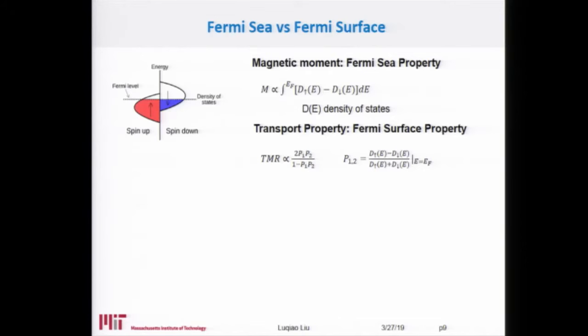For example, we talk about magnetic moment or magnetic susceptibility, and we know that this property comes from the whole Fermi sea. If you want to calculate the total moment of a certain material, you have to integrate over all of the density of states below the Fermi level. So basically, it's a Fermi sea property. At the same time, there are also properties that are only related to the Fermi surface. For example, most of the transport properties are only sensitive to the Fermi surface. If we talk about the tunneling magnetoresistance of a certain device, it's proportional to the spin polarization of the two magnetic layers you utilize. And the spin polarization here is only defined as the difference of the density of states at the Fermi level. So it has nothing to do with what happened below the Fermi surface.